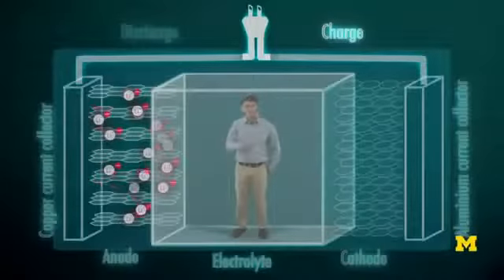So overall, you can think about the discharge and the charge cycle in a lithium ion battery as this rocking motion where lithium moves back and forth between the anode and cathode. And in fact, some people describe this battery as a rocking chair battery. Another bit of nomenclature is that we call this battery an intercalation battery because what we're doing is intercalating lithium ions into either the anode or the cathode with very little change in the structure of those anode and cathode materials. So essentially we're occupying vacancies within those materials without an enormous amount of swelling or structural change to the electrode materials. And basically that's it for lithium-ion batteries.